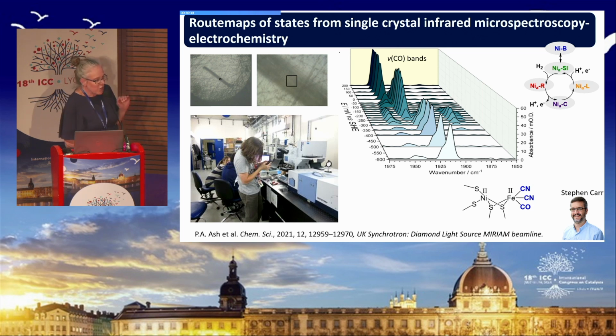And these are not quite the first set of spectra we recorded, but they look very similar to the very first spectra we recorded in those sorts of experiments. And so what you see here is that we're looking at the CO vibrational band, again from the active site. The cyanide bands are a bit further up here. The CO vibrational bands, as we step the potential for an electrode in contact with a single crystal of hydrogenase, and we're using the infrared microscope to focus the infrared on a little spot on that crystal. And so this is the crystal, a needle-like crystal lying on the electrode surface here, and the little black square zoomed in a bit more here is the area that we're sampling with the infrared, which is about 10 by 10 micrometers.